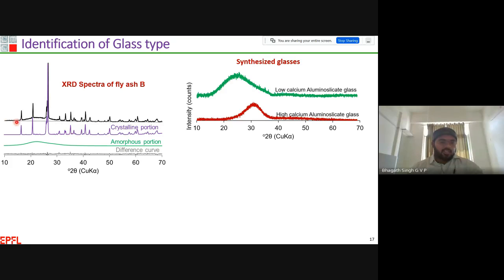This is one of the XRD spectra of fly ash B, and I have separated the total crystalline as well as the total amorphous portion by using Rietveld refinement. As you can see, I can clearly separate the crystalline portion as well as the amorphous portion. This is the amorphous portion of my fly ash. This is responsible for the reactive potential.